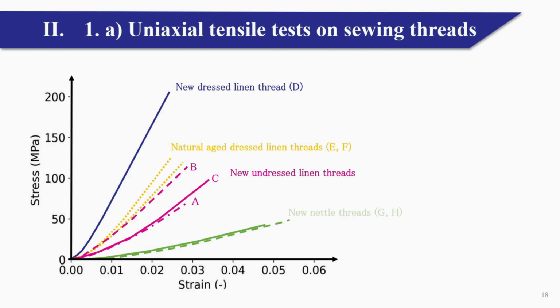Here, the results. The linen threads without finishing and aging are in pink. The linen thread B with 2 plies has a higher tensile strength than the thread C with 5 plies. Thread B is also more resistant and less extensible, despite coming from the same supplier as thread A and being finer, with the same number of plies, which is counterintuitive. The dressed linen thread D in blue showed the best stress-strain response, probably because dressing limits variability in diameter. However, the addition of a finish also raises questions regarding fiber aging, as demonstrated by the results for threads E and F in yellow. Finally, the nettle fiber threads G and H in green did not behave satisfactorily, probably because only single-ply threads could be found commercially.